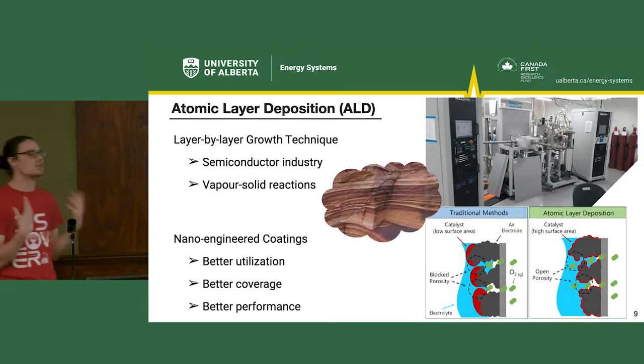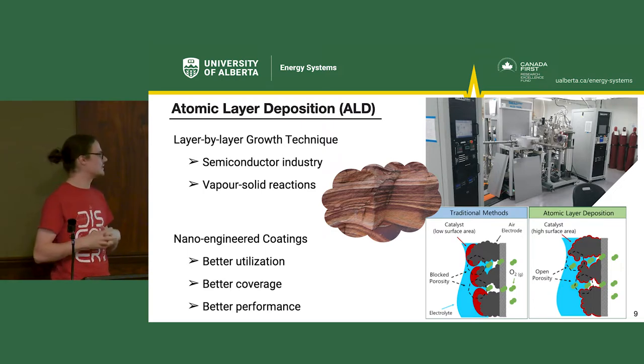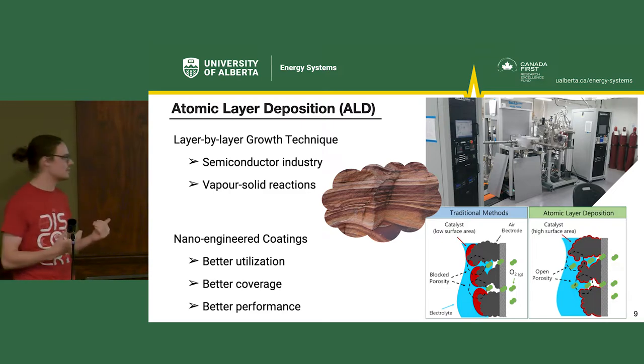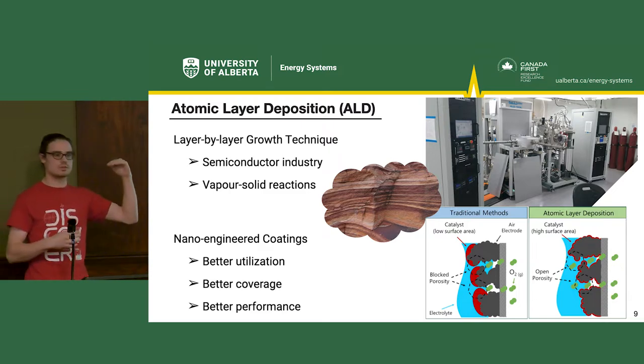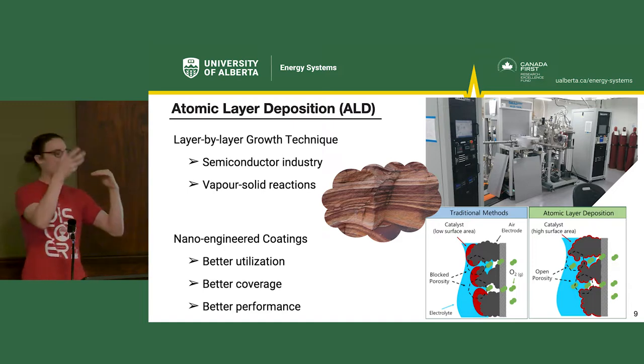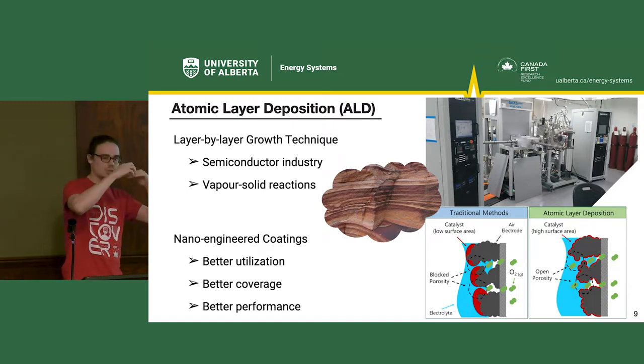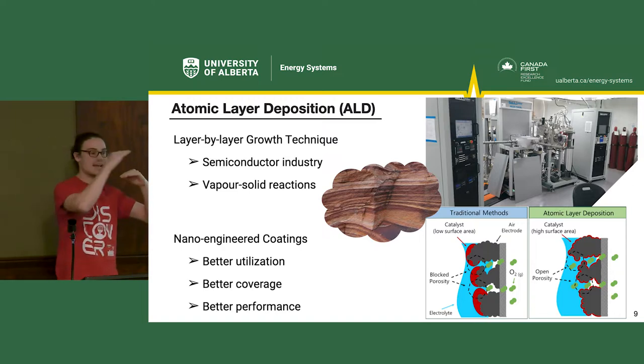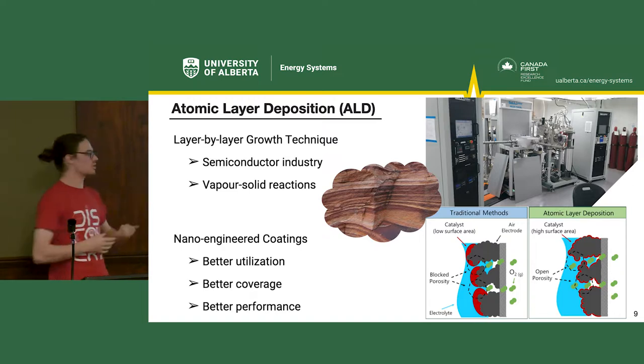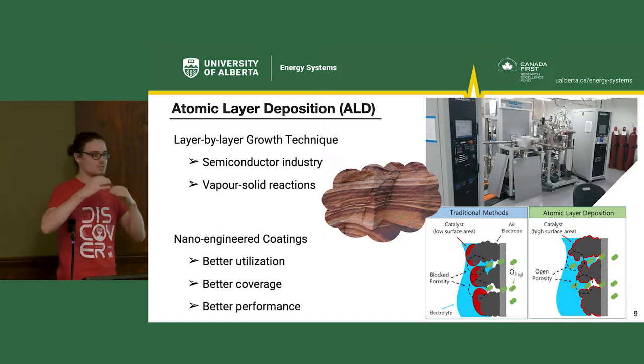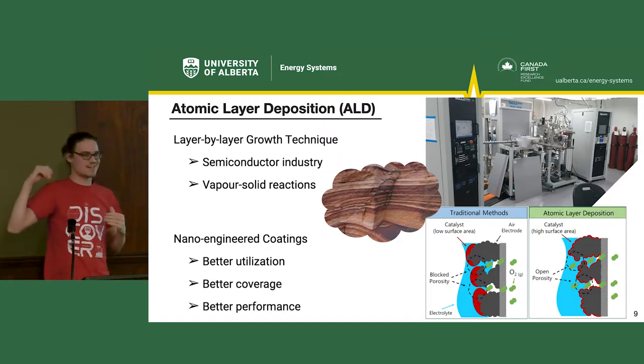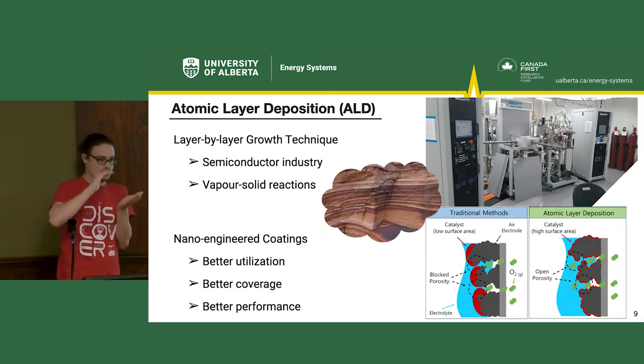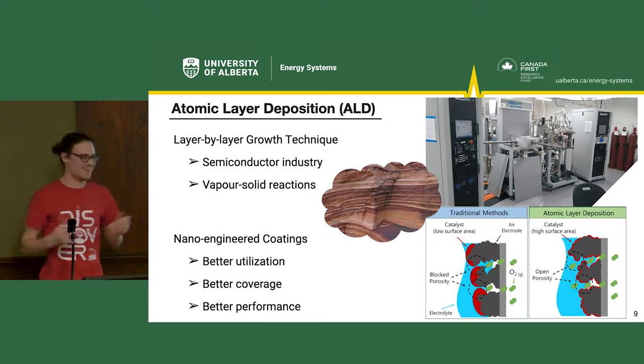So I do a nano engineering technique called atomic layer deposition, or ALD, I'll call it for now. And it's a layer by layer growth technique. So what that means is that I have a solid surface and I'll introduce a gas species. And so this gas will have my iron oxide and it will react with the surface and deposit an atomic layer, one atomic layer of my material. And that's it. And then I'll do another cycle and another next layer and so forth. So similar to how we have these rock formations over periods of years and years and years, I can create a material layer by layer over a period of seconds, right? So it's a lot more reasonable.